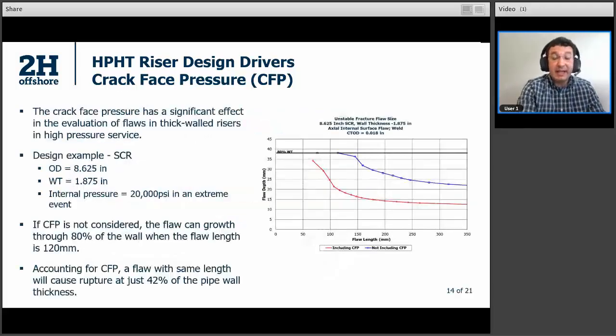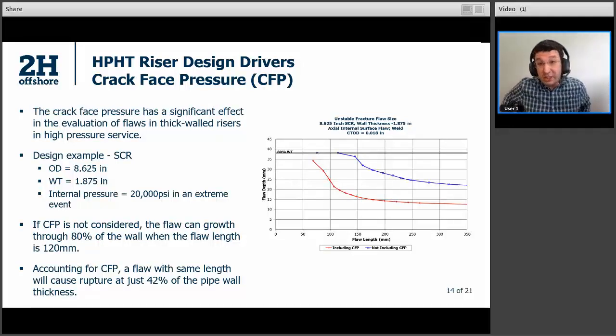There is an example here that I would like to share with you to demonstrate the effect of crack face pressure. The example is an 8-inch OD pipe, with a wall thickness of 1.9 inch and a design pressure of 20 KSI. This plot clearly shows that the blue line is the fracture limit of the SCR pipe without including the crack face pressure, and the red line is the fracture limit of the SCR pipe including the crack face pressure.